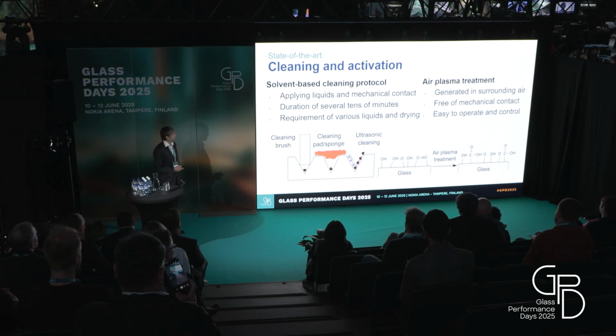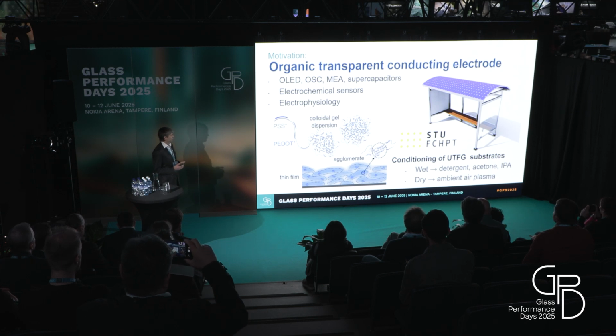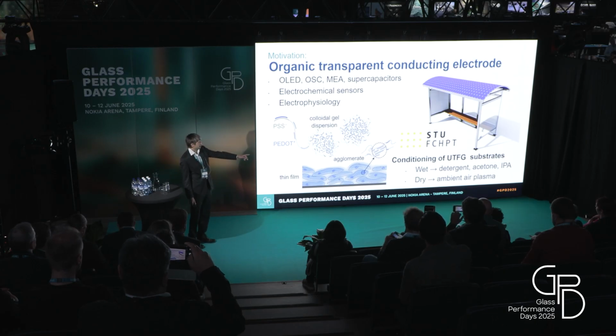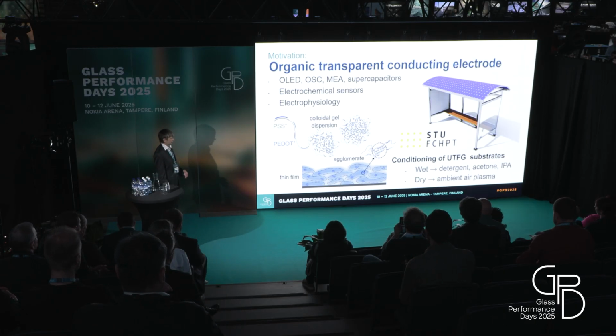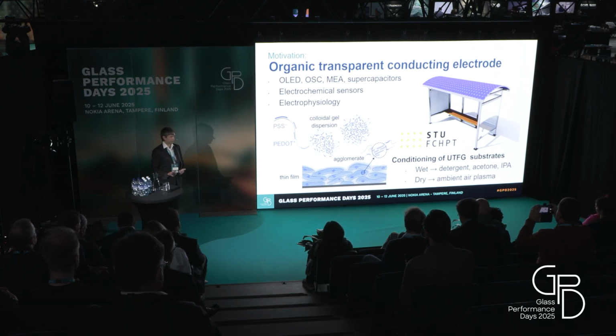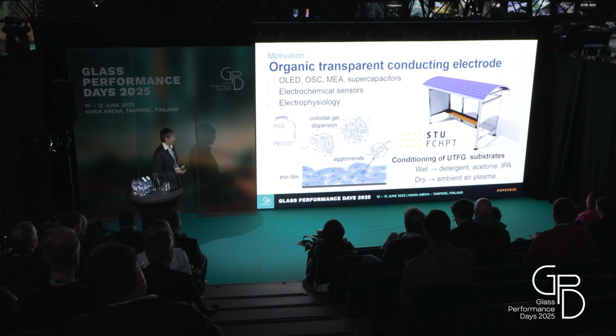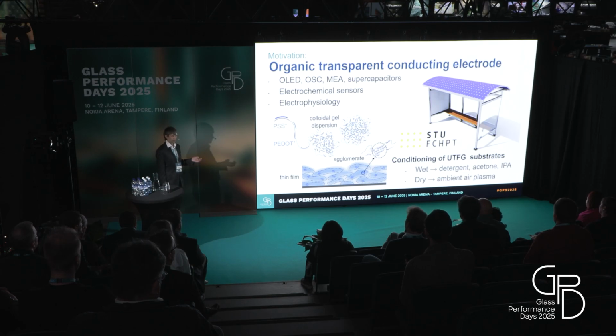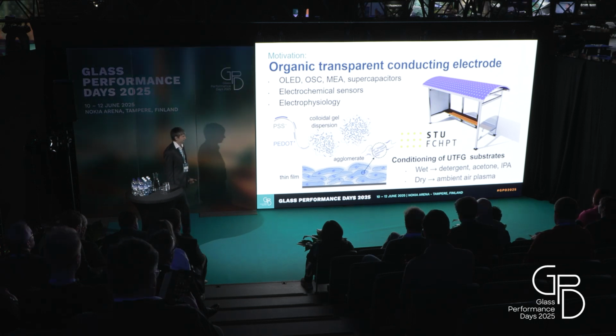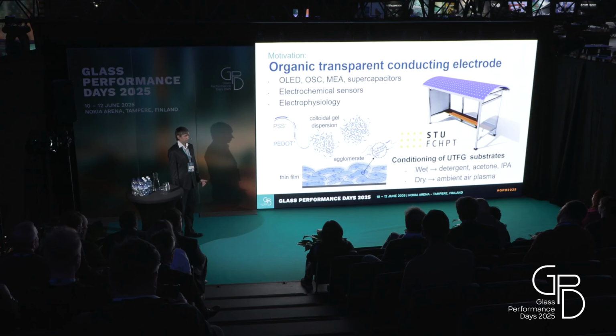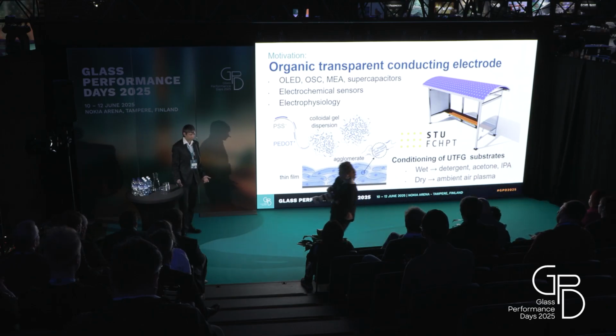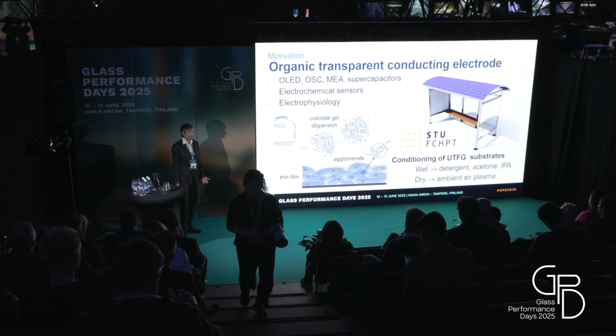And this solvent-based cleaning protocol, which we used for our coating dispersion, contained more liquids like detergent, acetone, or isopropyl alcohol. This is a standard cleaning protocol which is used at the chemical technology faculty in Bratislava, with which we cooperated, and they prepared the dispersions of PEDOT:PSS for us. PEDOT:PSS is a highly conductive and transparent polymer, which is suitable for flexible electronics. And the problem with organic conductive electrodes for such types of electronics is that they have a very short lifetime, because they are much more degradable by humidity.